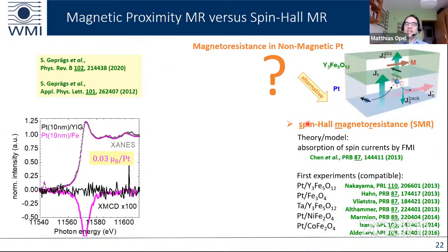And this alternative is the newly developed spin-Hall magnetoresistance effect. The model is based on the absorption of spin currents, and it was first formulated by Gerrit Bauer together with his PhD student Chen and published in 2013. In the meantime, many experiments have confirmed this theory. These are just some examples. These were the first experiments which were compatible with the theory. Experiments in platinum on YIG, platinum on magnetite, tantalum on YIG, platinum on nickel ferrite, and also platinum on cobalt ferrite.